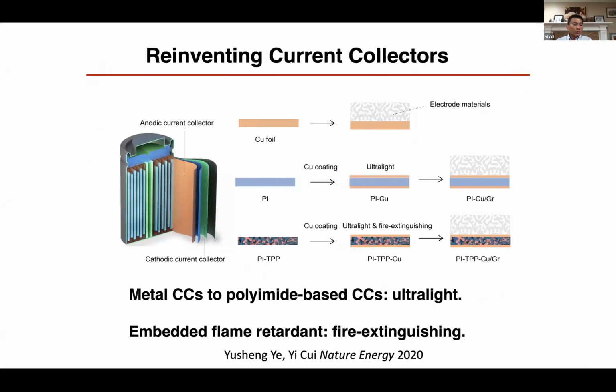So let me also share with you how to reinvent batteries. There's a possibility in every component we can reinvent. Let me just show you one example of reinventing the current collector. It's actually possible. Current collectors are copper foil, aluminum foil. So recently we said, well, let's replace this metallic current collector with plastic, but on top of that, coat a thin layer of metal, copper, top and bottom. Inside this plastic, this allows us to embed functions such as a fire retardant. And once the battery is about to catch fire, the temperature heats up, this comes and releases the fire retardant, making the battery completely safe.